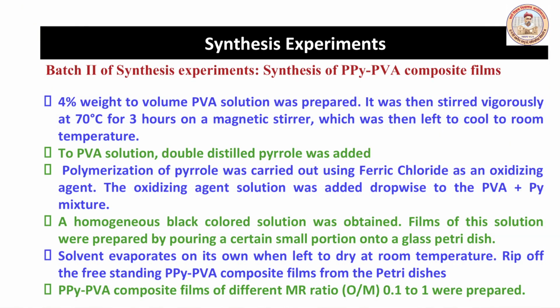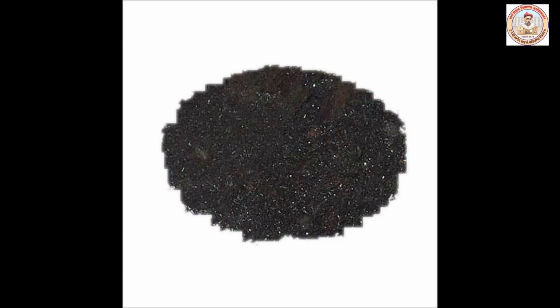In this, 4% weight to volume PVA solution was prepared. It was then stirred vigorously at 70 degrees centigrade for 3 hours on a magnetic stirrer, and then left to cool at room temperature. To the PVA solution, double distilled pyrrole was added. Polymerization of pyrrole was carried out using the oxidizing agent ferric chloride. The oxidizing agent was added dropwise to the pyrrole polyvinyl alcohol solution. A homogeneous black colored solution was obtained.